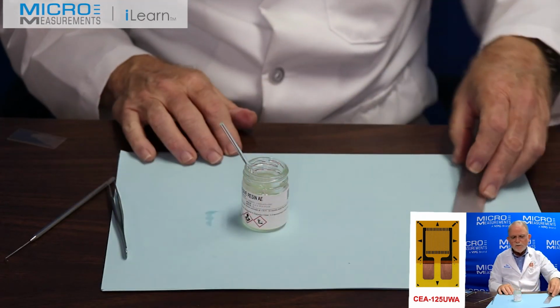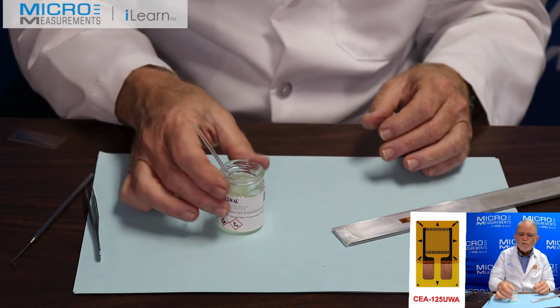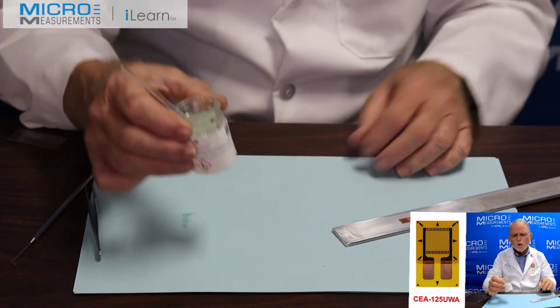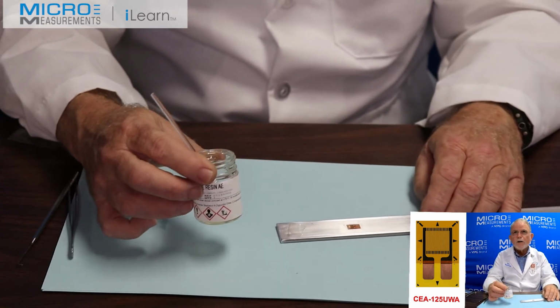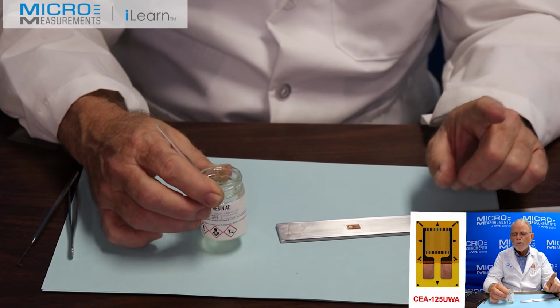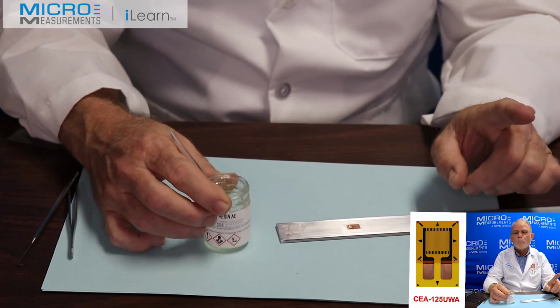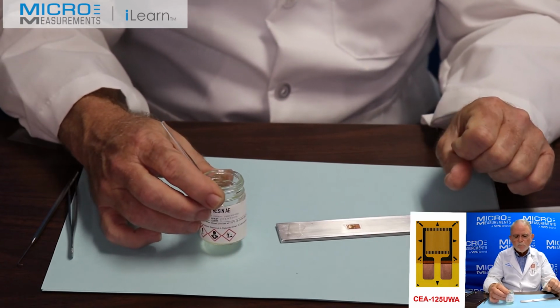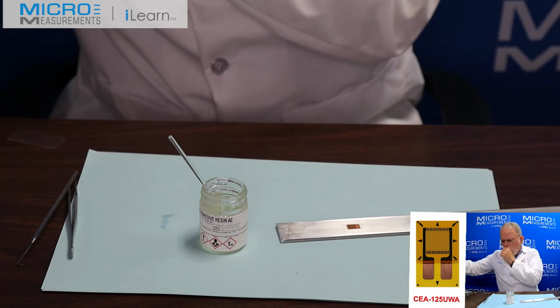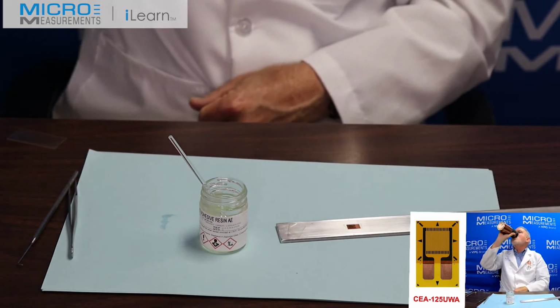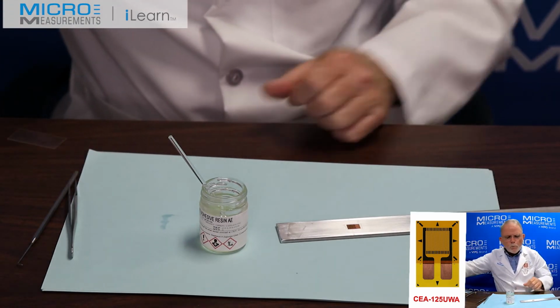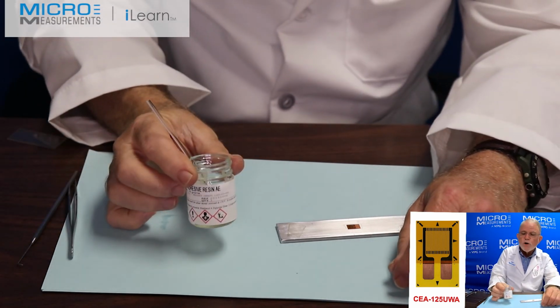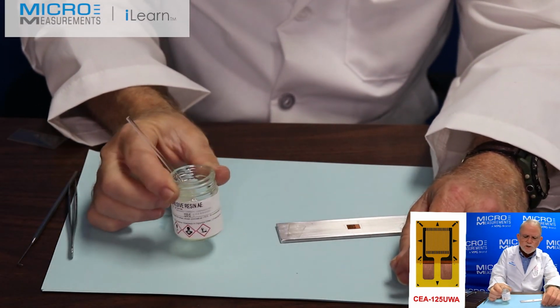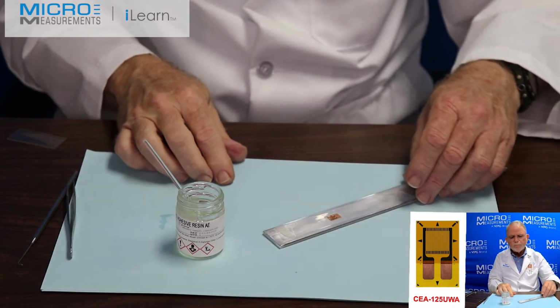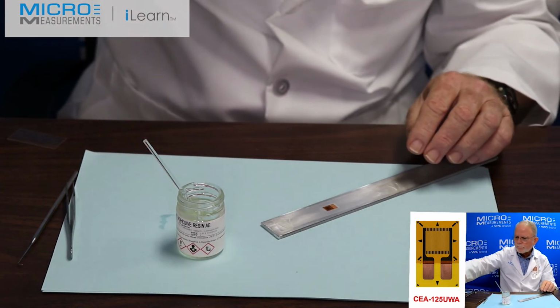All right, we have completed our 5 minutes of mixing. And if we were going to be using this material, the AE-10, at its minimum cure temperature and time, which is 75 degrees Fahrenheit for 6 hours, we would allow this to ingest for another full 5 minutes. But since I'm going to clamp this up and leave it overnight, I will not have to do that.